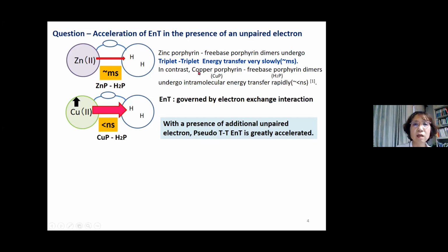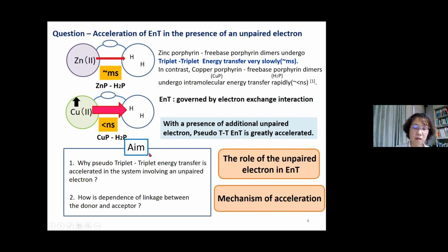In contrast, in copper porphyrin, which has an unpaired electron in the ground state, the copper porphyrin and free base porphyrin dimer undergo intramolecular energy transfer very rapidly. So with the presence of an additional unpaired electron, triplet-triplet energy transfer is greatly accelerated. So the aim of this talk is why the triplet-triplet energy transfer is accelerated in the system involving an unpaired electron, and how it depends on the linkage between the donor and acceptor. So the role of the unpaired electron, and I would like to also clarify